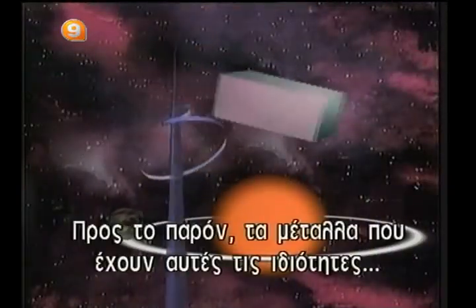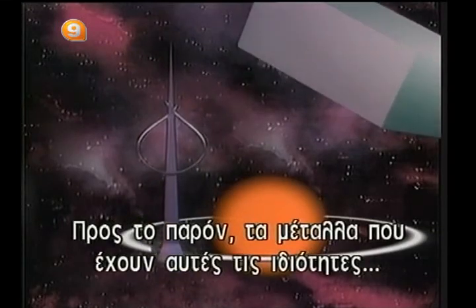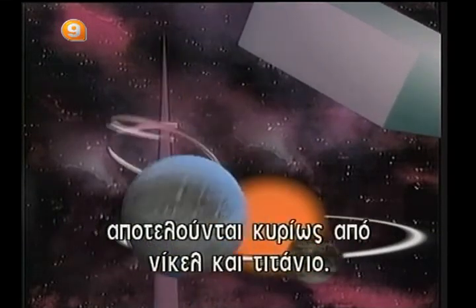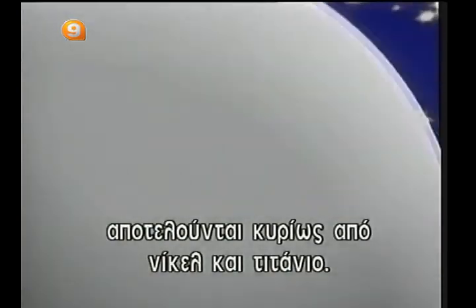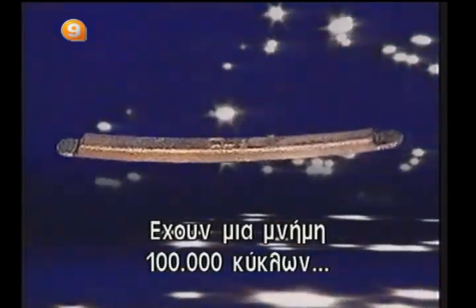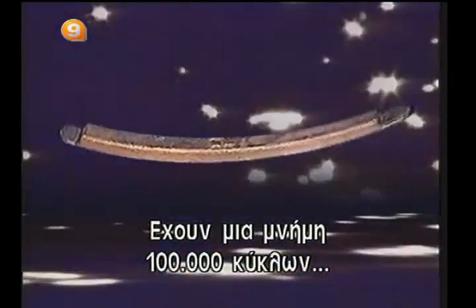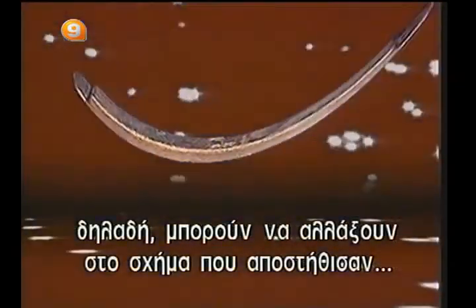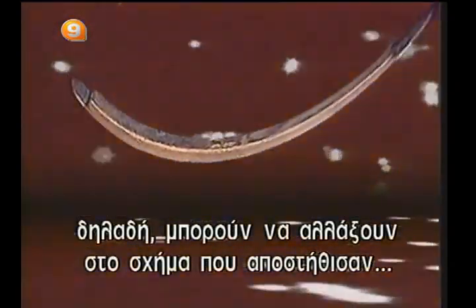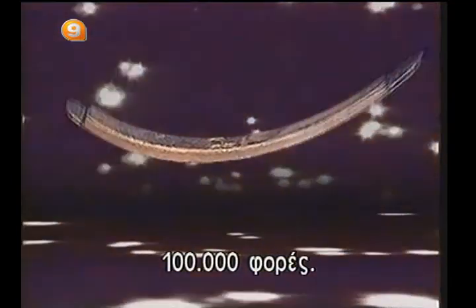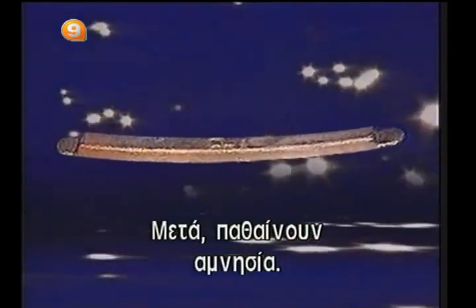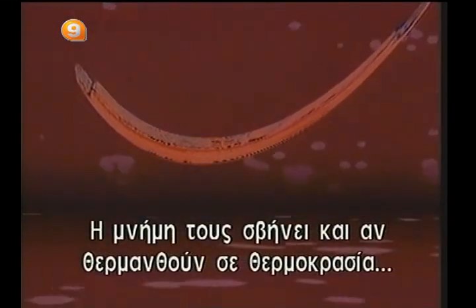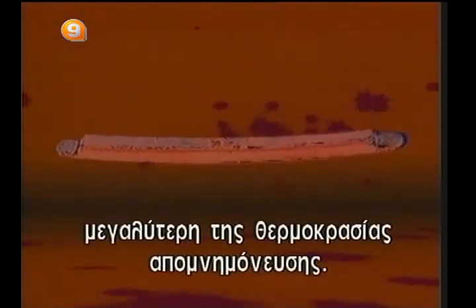At present, the best alloys displaying this property are mainly composed of nickel and titanium. They have a memory of 100,000 cycles, meaning they can reconstruct a learned series of shapes 100,000 times. After that, they become amnesic. Their memory can also be erased simply by heating the work beyond the memorization temperature.